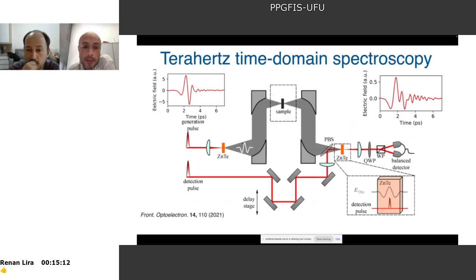In practice, all this experimental part with terahertz pulse will be closed in a box because humidity absorbs many frequencies in the terahertz range, and then you need to keep all this experimental setup in a purged box without humidity. So we use parabolic mirrors like this. So this mirror collimates the light and makes it parallel, and this one here focuses the terahertz pulse in the sample. In this case, we are using transmission geometry, so the light goes through the sample and then is collected by this parabolic mirror and goes here to this detection part of the setup.